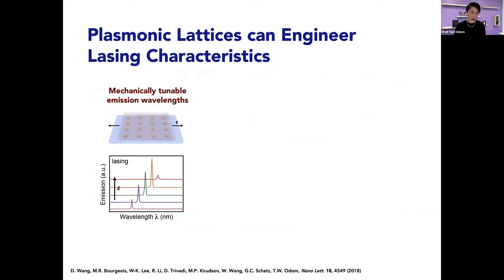Okay, so what other lasing characteristics can we feature that highlight the flexibility of this system? The first one is we can mechanically tune the wavelength of emission by patterning these gold nanoparticles onto polydimethylsiloxane, which is an elastomer, and you can apply in-plane strain. If you apply in-plane strain, the distance between the particles increases, which is why the wavelength of lasing increases. And this is where the advantage of having liquid gain comes in. So even as you're stretching the solid substrate, the liquid can always be surrounding the metal nanoparticles. So molecules are always in the hot spots that can be used for lasing, which is sort of a nice system.